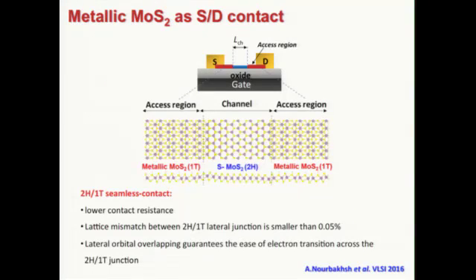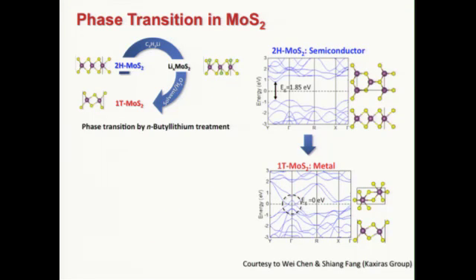To solve this problem, we use metallic molybdenum disulfide as the contact. So we design a device structure like this. We have a metallic MoS2 as the immediate contact, and a semiconducting MoS2 as the channel. The good thing here is that we have a seamless junction, so both regions are covalently bonded together, and the mismatch between them is very small. So it's sort of a homojunction. Well, yeah. How do you make it metallic? That's what I'm going to explain here.